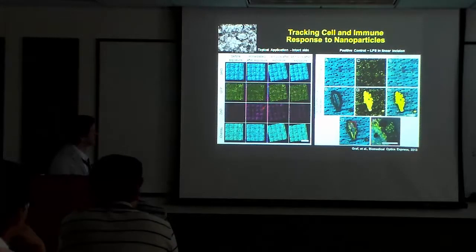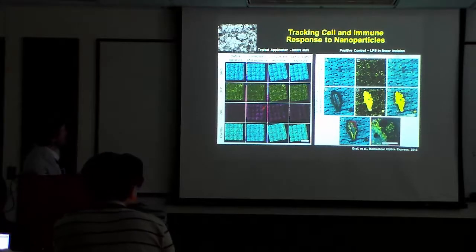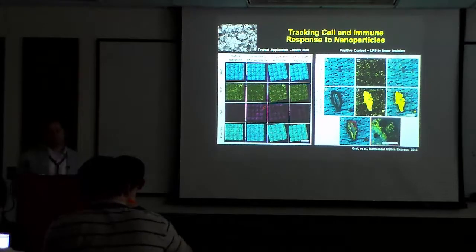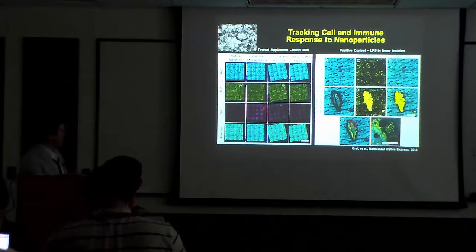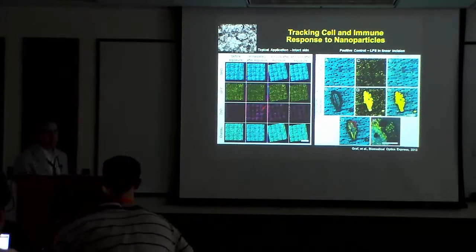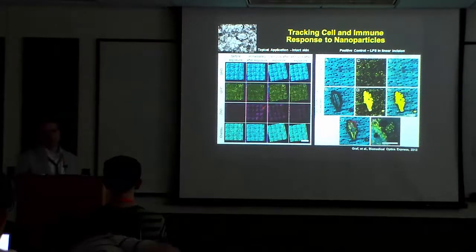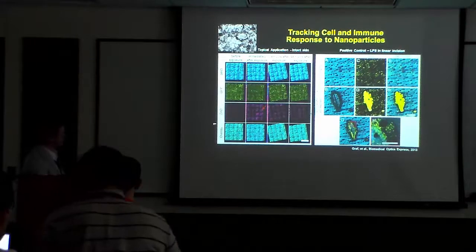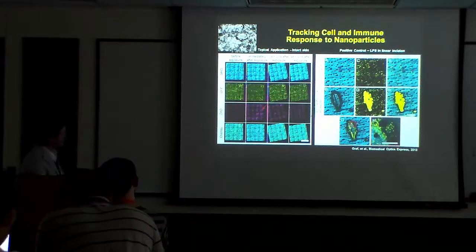Well, we use this system to look at that. And fortunately, the zinc oxide produces a 2-photon luminescence signal. If you hit it with this titanium sapphire with an ultra short pulse, it will actually luminesce and produce its own signature. And so we can have a channel that's specific for zinc oxide.